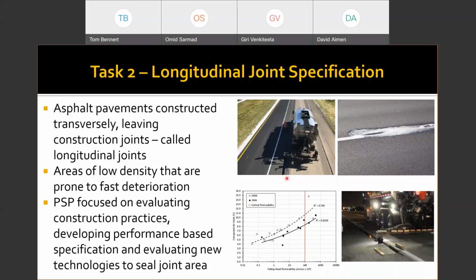Unfortunately, with construction practices in general, we end up seeing that along these edges we have an area of low density, what we call high air voids in the asphalt industry. And that allows water to get in. You can see here the picture on the right, which I love, by the way. This is actually ice that's formed on the surface from water that is essentially freezing and expanding up and out of a longitudinal joint. So this was water that was actually trapped in the joint that during a freezing cycle in the winter has actually pulled up and out of the longitudinal joint area.